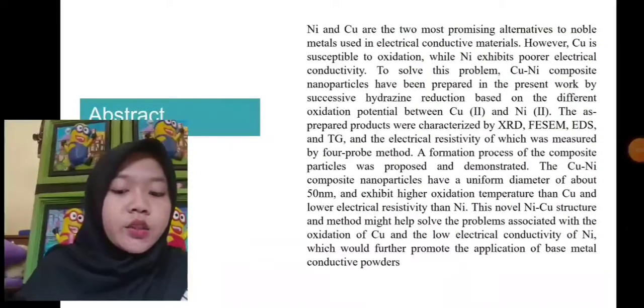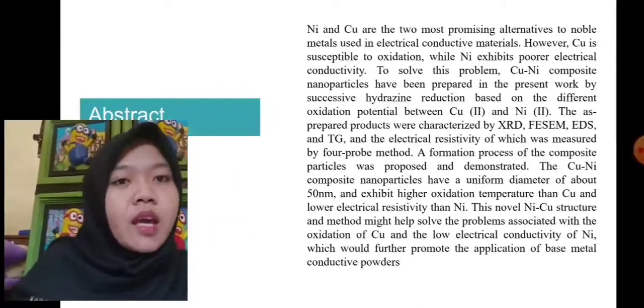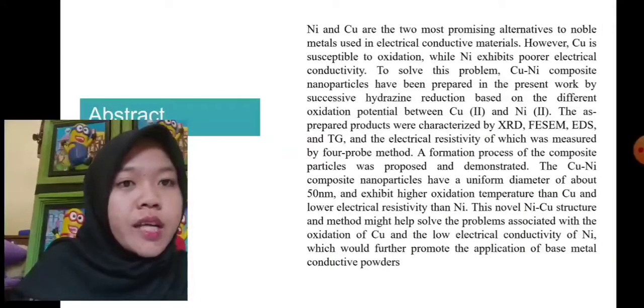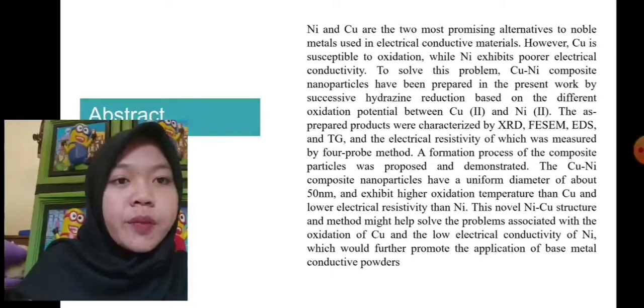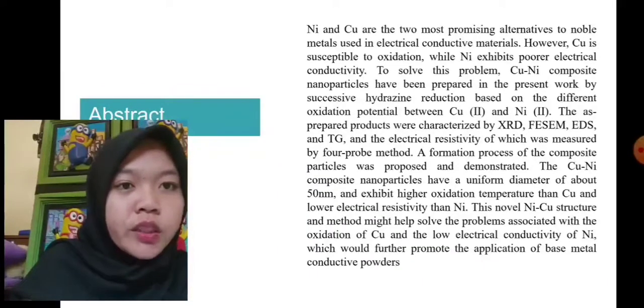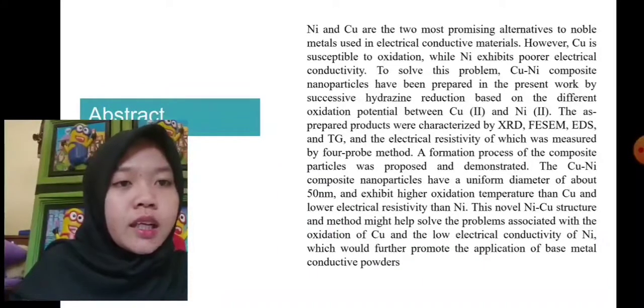Okay, let's go to the abstract of this article. Nickel and copper are the two most promising alternatives to noble metal used in electrical conductive materials. However, copper is susceptible to oxidation, while nickel exhibits poor electrical conductivity. To solve this problem, copper-nickel composite nanoparticles have been prepared in the present work by successive hydrazine reduction based on the different oxidation potential between copper 2 and nickel 2.